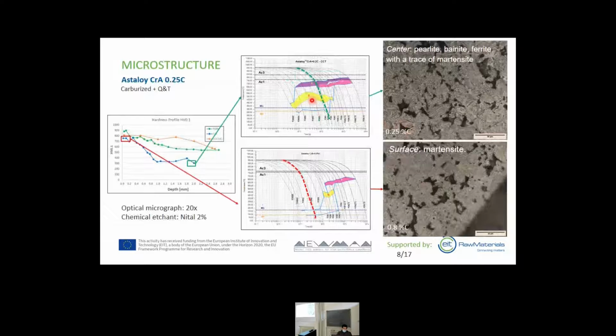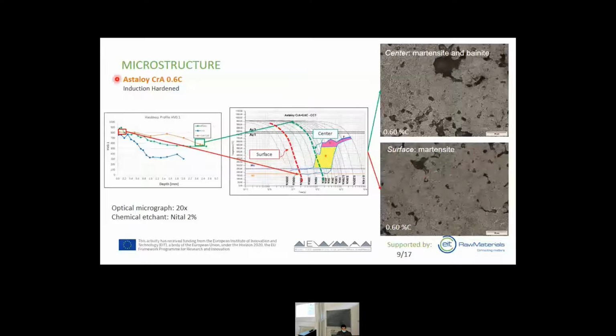For the same reason, the microstructure of the Astalloy CRA with 0.25% of carbon is a mixture of pearlite, bainite, ferrite, and some martensite at the core of the samples, while the same sample is completely martensitic near the surface due to the cooling rate and the carbon content. And finally, the microstructure of the Astalloy CRA with 0.6% of carbon is martensitic-bainitic at the center of the samples, while it is martensitic on the surface due to the different cooling rate between the center and the surface.